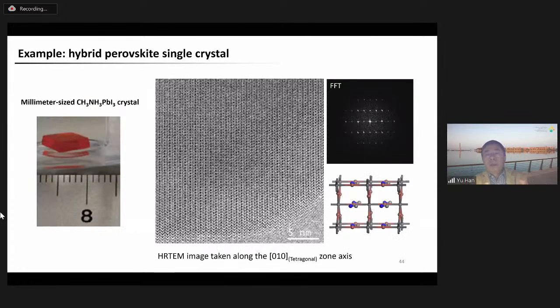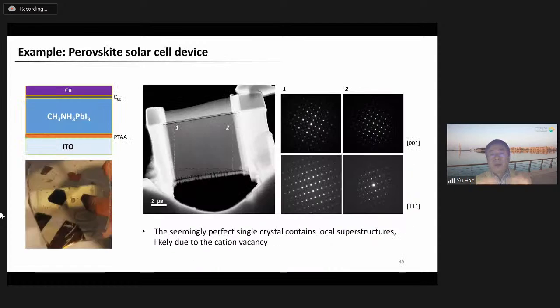So using cryo-FIB, we have prepared a TEM specimen from a millimeter-sized hybrid perovskite single crystal, which allowed us to acquire high-resolution images at nearly atomic resolution. And cryo-FIB can also be used to prepare a TEM specimen from a real device. For example, in this case, we cut a very thin slice from a perovskite-based solar cell device. This is a real device, and this device is based on a single crystal perovskite as the active layer, active material.